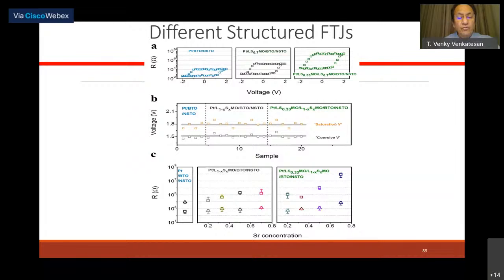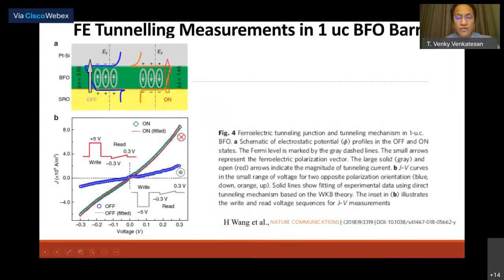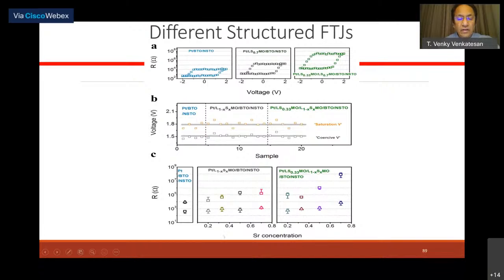Now, if you look at the actual resistance in the on and the off state, what you see is that when you change the number of buffer layers, the so-called on-state resistance, which is really the lower resistivity state, doesn't change dramatically, but the off-state resistance changes dramatically, and that is the reason why the on-off ratio increases.